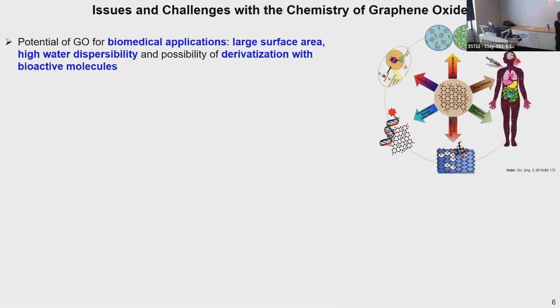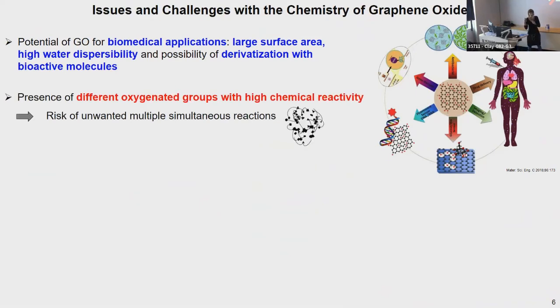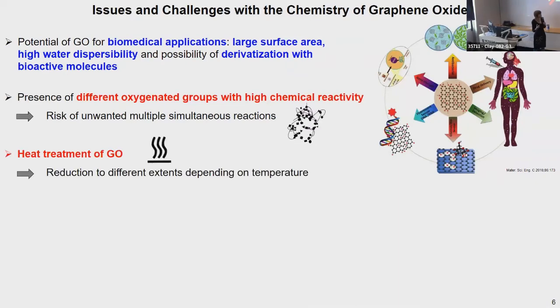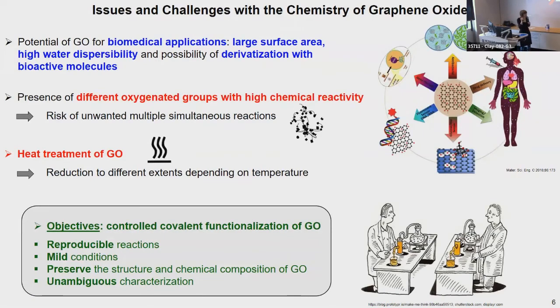But when we started to work on the functionalization of graphene oxide, actually we faced many issues. This is related to the fact that graphene oxide has different oxygenated groups on the surface having a rather high chemical reactivity. So there is a risk of unwanted multiple simultaneous reactions. In addition, some reactions might require heating, but graphene oxide is thermally unstable. So the material can be reduced to different extents depending on the temperature. In this context, our objectives are to control the covalent functionalization of graphene oxide using reproducible reactions that can be performed in mild conditions, allowing us to preserve the structure and the chemical composition of the material. And also one of our objectives is to characterize the functionalized graphene oxide unambiguously, because you will see that this is very challenging.